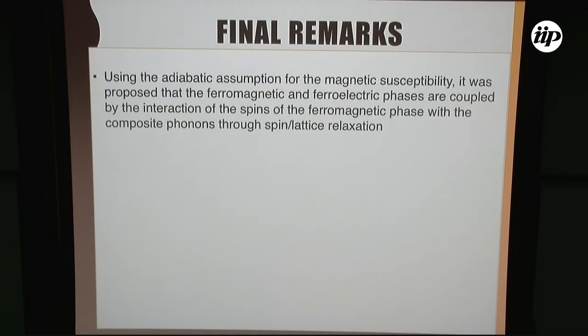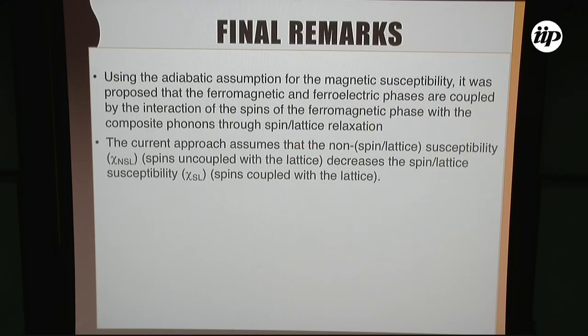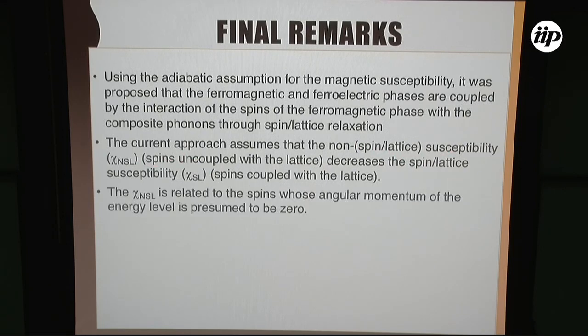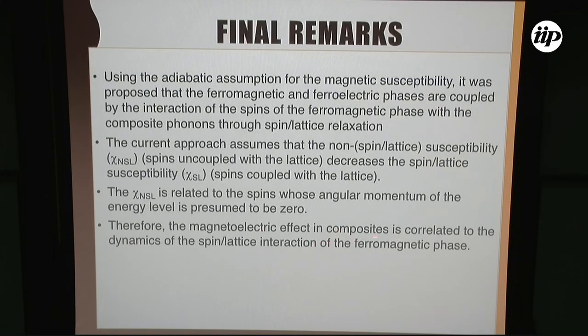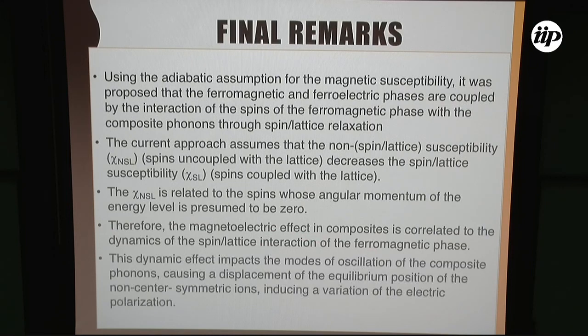My final remarks: using this adiabatic assumption of magnetic susceptibility, the proposal is that the ferromagnetic and ferroelectric phases are coupled by interaction of the spin of the ferromagnetic phase with composite phonons through spin-lattice relaxation. This approach assumes the non-spin/lattice susceptibility: the spin not coupling with the lattice decreases the spin-lattice susceptibility. The magnetoelectric effect in the composite is correlated with the dynamic spin-lattice interaction of the ferromagnetic phase. This dynamic impacts the modes of oscillation, the composite phonons, causing a displacement of the equilibrium position of non-centrosymmetric ions, inducing variation of the electric polarization, and as a consequence the magnetoelectric effect.